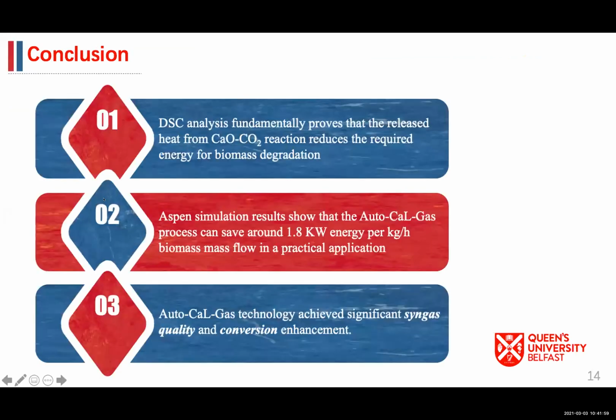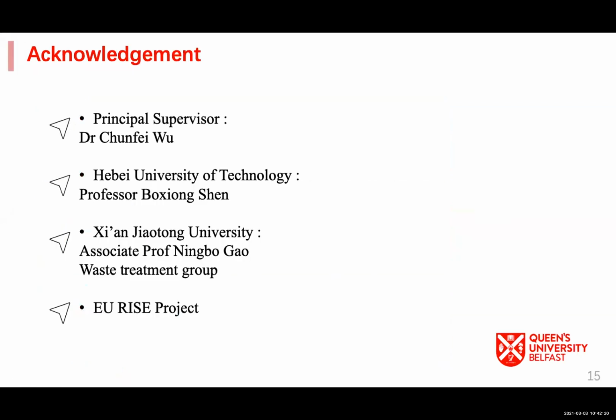So to summarize, the DSC analysis fundamentally proves that the released heat from calcium oxide carbonation reduces the required energy for biomass degradation. Aspen simulation results show that our process can save around 1.8 kilowatt energy per kg per hour biomass mass flow in a practical application. And our process achieves significant syngas quality and conversion enhancement.